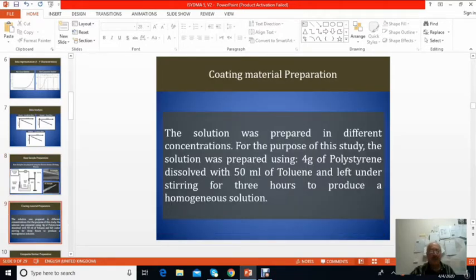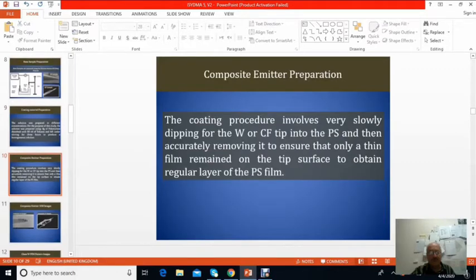Coating materials preparation. The solution was prepared in different concentrations. For the purpose of the study, the solution was prepared using 4 grams of polystyrene dissolved in 50 ml of toluene and left under stirring for 3 continuous hours to produce a homogeneous solution. Composite emitter preparation. The coating procedure involved dipping very slowly. It's important to dip very slowly, because if you don't, a ball will form, a drop will form at the edge of the tip. So very slowly dipping the tungsten or carbon fiber tip into the polystyrene, and then accurately and vertically removing it to ensure that only a thin film remained on the tip surface to obtain regular film.